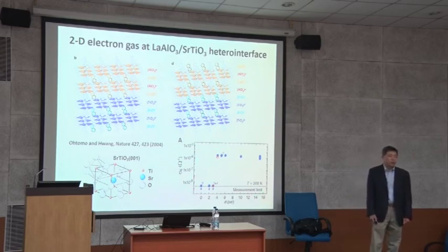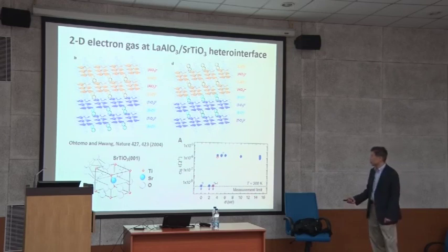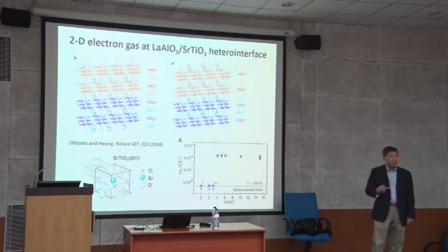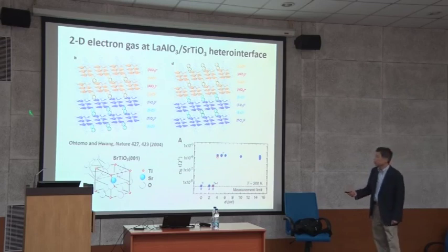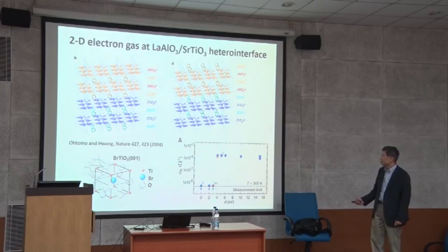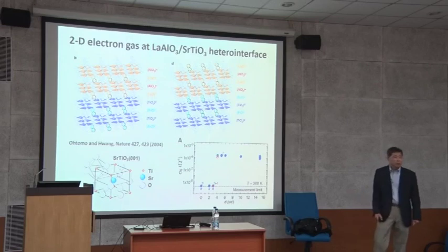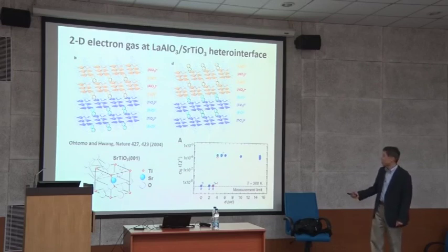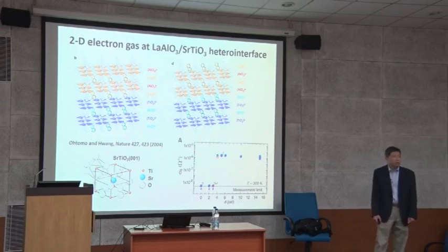at the Max Planck Institute actually measured this interesting phenomenon. When you grow lanthanum aluminate layer by layer, making one layer, two layers, three layers, four layers, they increased the thickness of the lanthanum aluminate, like how many unit cells, okay? On top of the TiO2 terminated surface, they grew a number of unit cells and increased it. Below 3 unit cells, that is 1, 2, 3 unit cells, it's insulating. Okay, but suddenly, once you pass 3 unit cells, it jumps to a very highly conducting 2D electron gas, and this conductivity then doesn't change as a function of the thickness of the lanthanum aluminate.